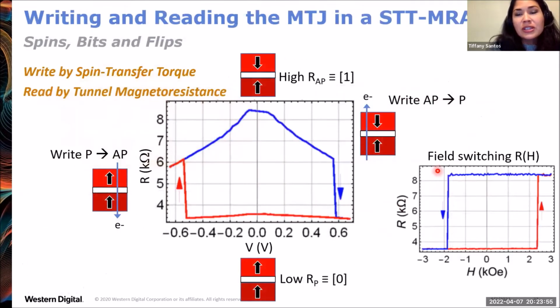Okay. And so this is kind of a demo of the writing and reading of the magnetic tunnel junction in the STT MRAM cell. I'm showing here resistance versus voltage. We can start here at low bias and in the high resistance state, which is anti-parallel alignment of the two ferromagnets, or for example, a written bit of 1. When a voltage is applied to write from the anti-parallel to the parallel state, you have the voltage surpassing the critical voltage needed for switching, and we get to the parallel state or the low resistance state, for example, a written bit of 0. And then when you want to flip back to the anti-parallel state, you apply a voltage in the opposite polarity to flip back to the high resistance state.